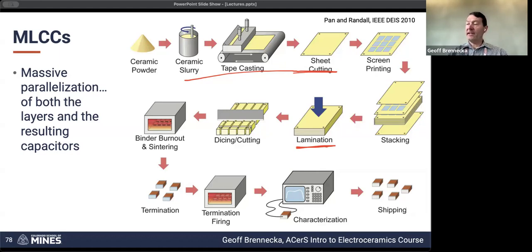One trick that is often used here is to add just a little bit of the parent solvent between each of these layers to help those fuse together. You use too much and you lose all of the nice clean lines from your screen printing. So you don't want to put too much of that solvent in there and make everything gooey, but you want to add just enough to assist with a little bit of interlayer diffusion, so that during this lamination step, you start with a bunch of discrete layers and you end up with one solid body that used to be layers and is now all coherent together. And you need that to be coherent, because the next step is to go through and dice it up.